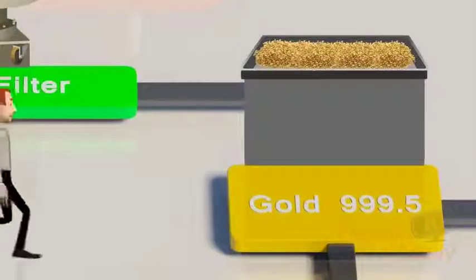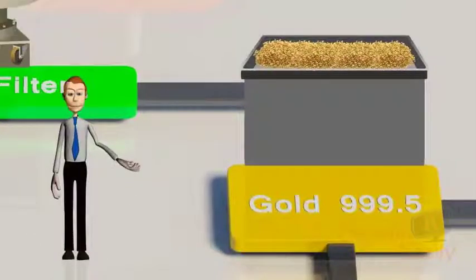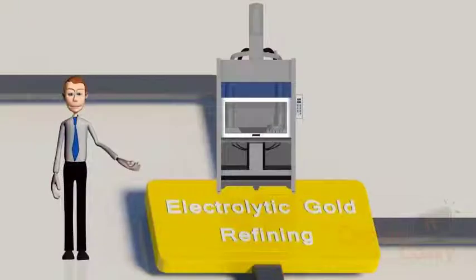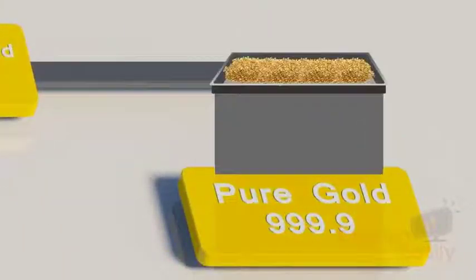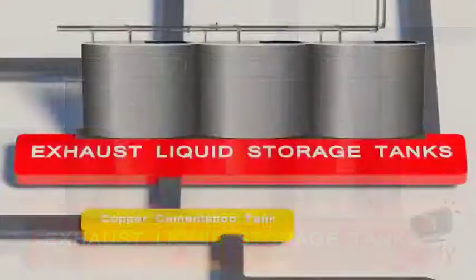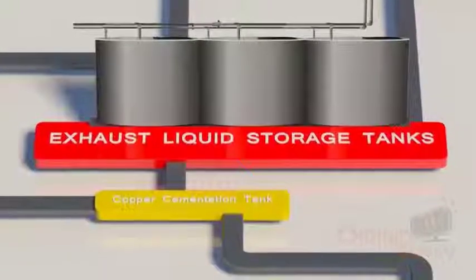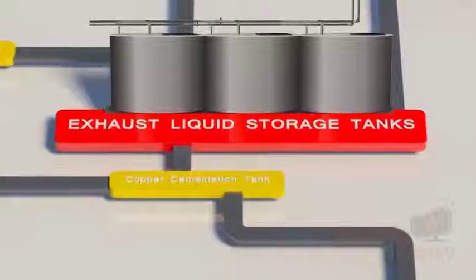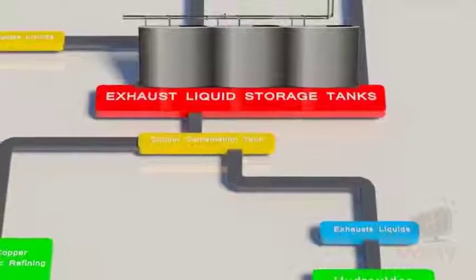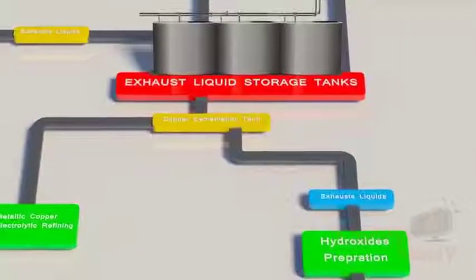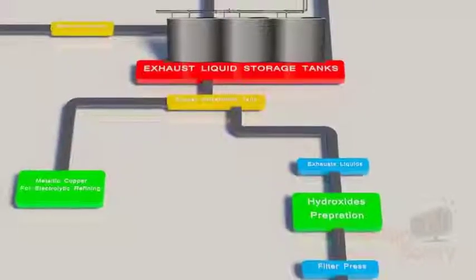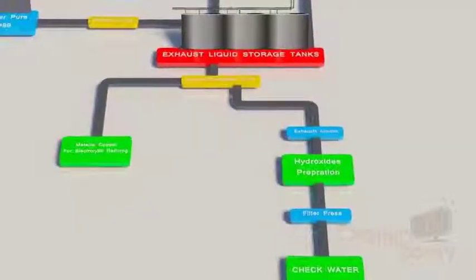Pure gold of 999.5 quality filtered from aqua regia refining plant, if it needs to be further purified, should pass through the process of electrolytic gold refining in order to get 999.9 purity. All the exhaust liquids are collected in storage tanks, are passed through 3 tanks by overflow systems, and then primarily in the first stage, copper is cemented, which is filtered and collected for further refining. The exhaust liquids after copper cementation are treated with alkali solution mixture of calcium and sodium hydroxide. These metallic hydroxides are sedimented, which are filtered in a filter press, and then after, clear water is discharged to drain.